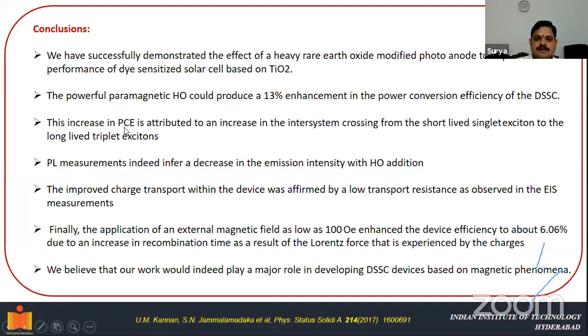And this increase in the photo conversion efficiency is attributed to increase in intersystem crossing from the short-lived singlet exciton to long-lived triplet excitons. The photoluminescence measurements indeed infer a decrease in the emission intensity with the holmium addition. The improved charge transport within the device was affirmed by a low transport resistance as observed in the electrochemical impedance spectroscopy measurements. Finally, application of external magnetic field as low as 100 Oersteds enhanced the device efficiency to